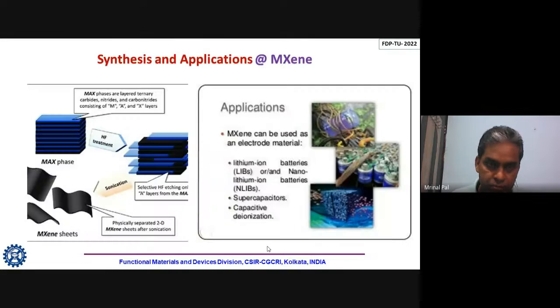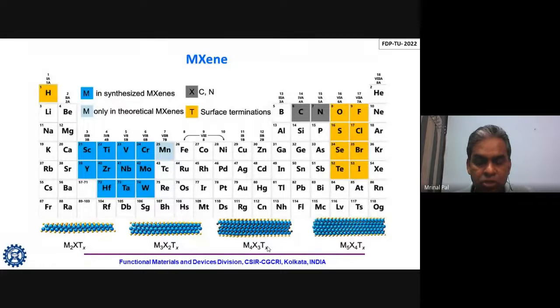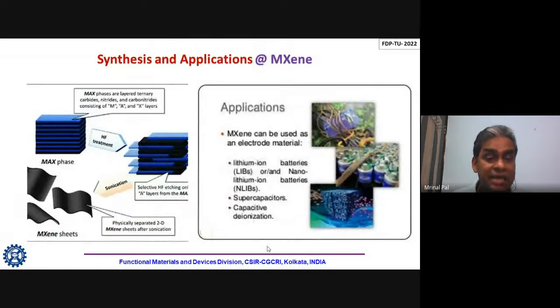What is this? Basically, it is also made from a 3D material. From bulk, we prepare all those things. The bulk phase is called the MAX phase. From this MAX phase, M, A, and X stand for three different types of elements, which I showed in my previous slide, the periodic table. So this is called the bulk MAX phase. By etching that MAX phase using something like hydrogen fluoride, we make the Z-axis stacking very weak, and after that we use an ultrasonic technique so that the layers can come out, and in principle you can get a single layer of MXene. So this is from MAX phase to MXene.